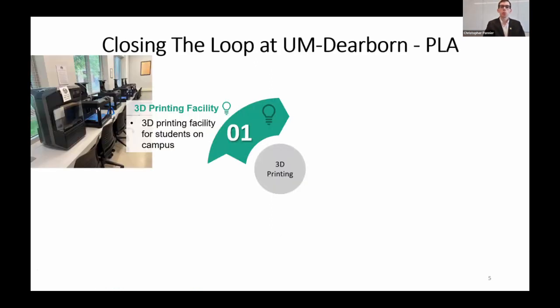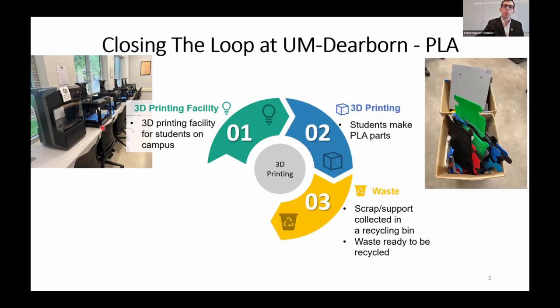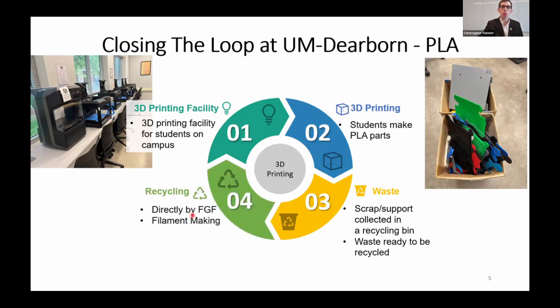So we're closing the loop on campus at U of M Dearborn. We're cycling PLA, polylactic acid polymer. So we have a machine shop with a 3D printing lab attached to it. So there's a whole fleet of MakerBot 3D printers. And the older MakerBots don't even have a heated build plate. So the students have to print a raft for every part they make. That means there's a lot of scrap PLA. When the students are making their parts and discarding the rafts, we've put in a collection system so we can take failed parts or excess rafts, collect the scrap, and then recycle it on campus, either directly as fused granule fabrication or by making our own filaments.